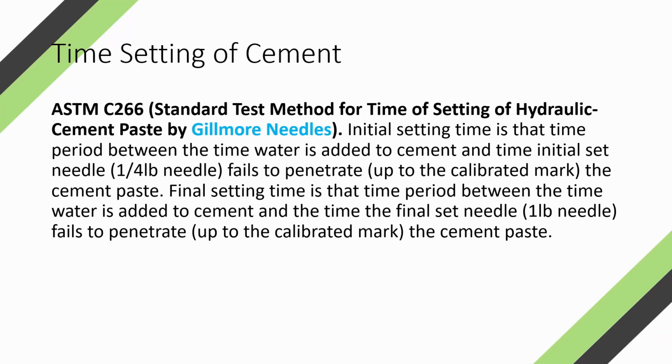And the final setting time naman is the time period between the time water is added to cement and the time the final set needle fails to penetrate the cement paste. So yung weight naman ng ating final set needle is 1 pound.